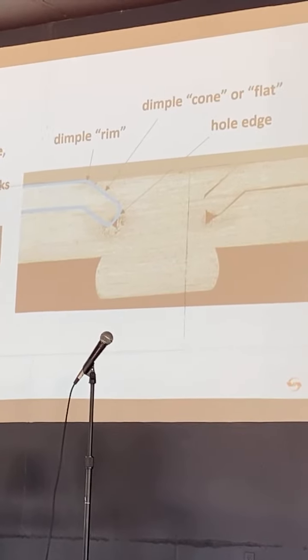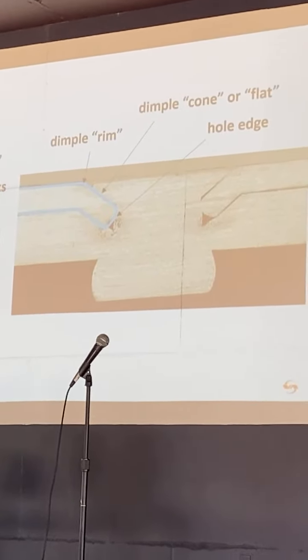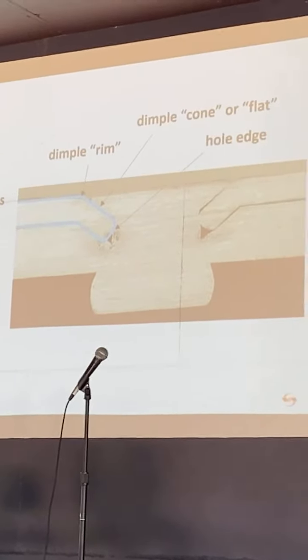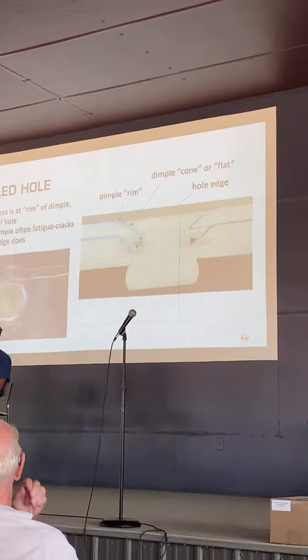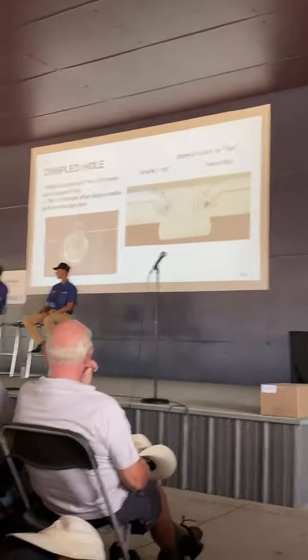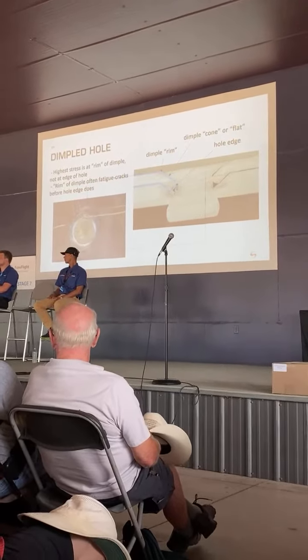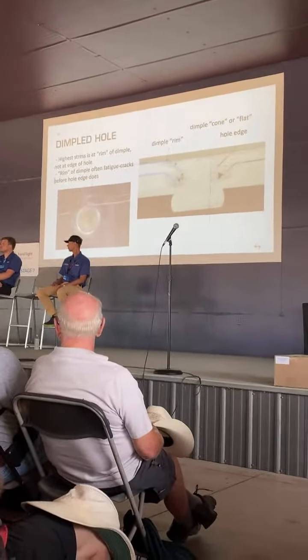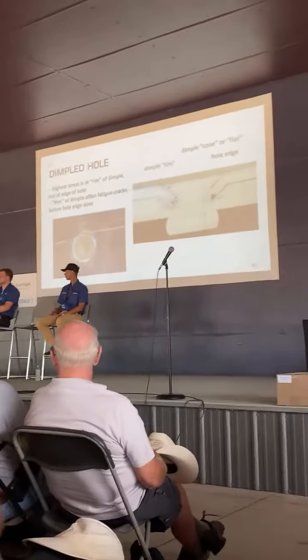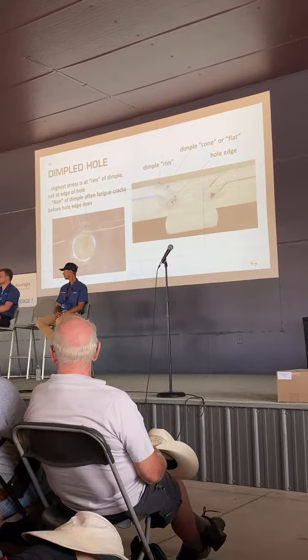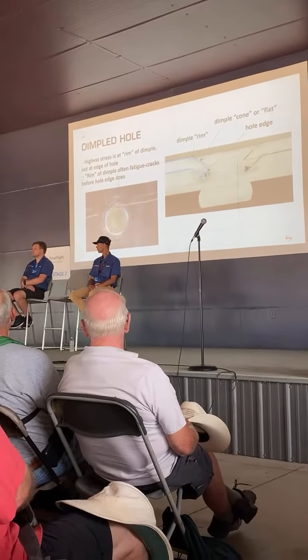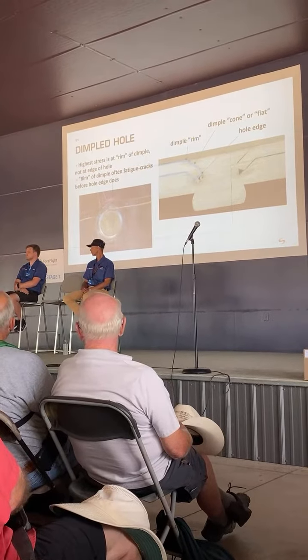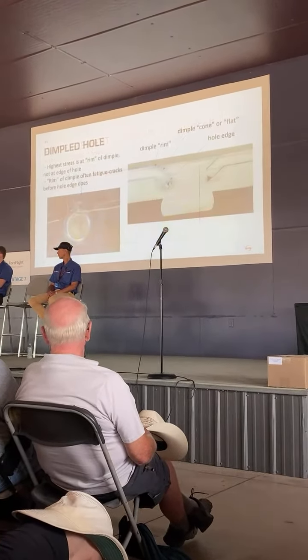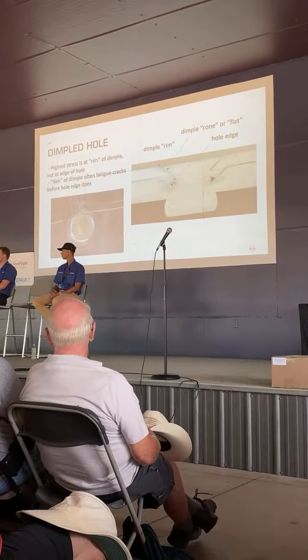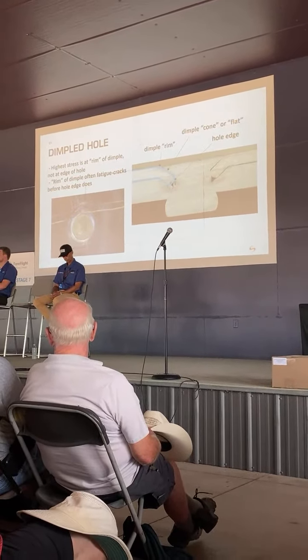So the highest stress, and I'll show a finite element analysis model of this in a subsequent slide. Finite element analysis is observing the part inside the computer, dividing it up into little segments, and you can see how the stress flows through. So it mathematically calculates the stress in different areas of the part. But what we're seeing is that often the highest stress point in this rivet is up here on the rim of the dimple, and the failure will go through the rim of the dimple. And this is what we've seen from the early days, even back to 1999 when we first conducted testing, trying to get to the point where we could punch holes at final size.